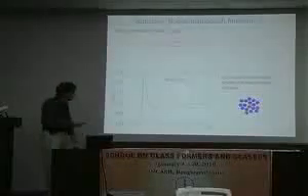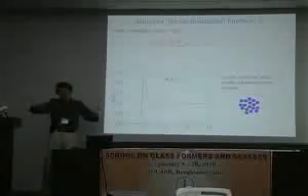Now, the g of r is useful to characterize the structure on very short distances. First nearest neighbor shell, the second nearest neighbor shell. Now, if you are interested in larger distances, this g of r is no longer interesting, because if you look at it, it basically becomes just flat. If there is a superstructure at larger distances, you don't see it anymore.